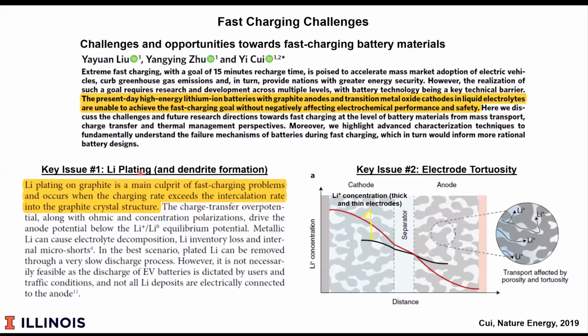And the reason in graphite anodes is that there's very little driving force for lithium to go into graphite. It's only a few tens of millivolts. And so if you go from a metal anode where we want to plate metal but not grow dendrites, if we go to a conventional graphite anode, if the lithium comes into that anode faster than it can diffuse in and be reduced, it will form a dendrite on the surface.